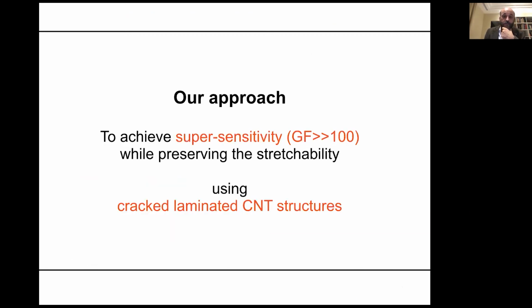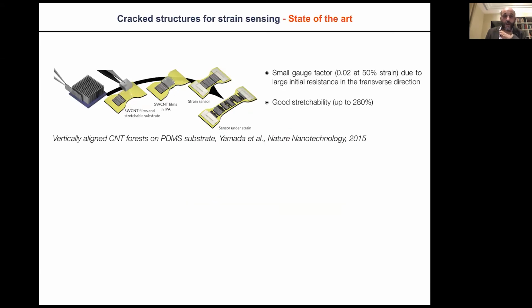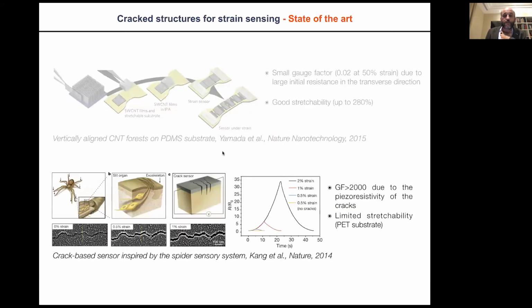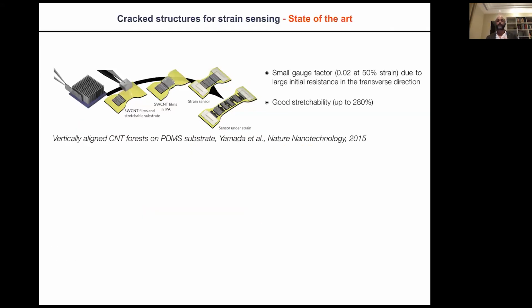So the approach that we used here was really a mechanical engineering approach coming from composites. That means the point was to achieve the super sensitivity by using cracks in laminated structures. This is something that really comes more from the composite world. And the point here is really to make sure that by introducing cracks into the structures, we can preserve the stretchability.